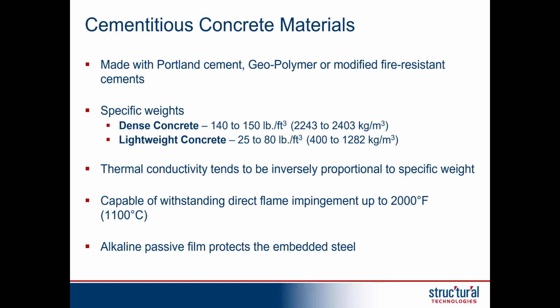And when we classify these cementitious fireproofing materials, specifically when it's related to concrete, we either go dense or lightweight, with the dense being, I just used the English nomenclature, I should say American, 140 to 150 pounds per cubic foot versus the lightweight 25 to 80 pounds per cubic foot. What's interesting about that is the thermal conductivity tends to be inversely proportional to the weight, meaning that the lightweight concrete typically performs better in a fire test than the dense concrete, and that's because there's more porosity that's locked into the cementitious matrix or the cement paste. And with that porosity, that means air, and then that air is going to act as an insulator, which is terrific.